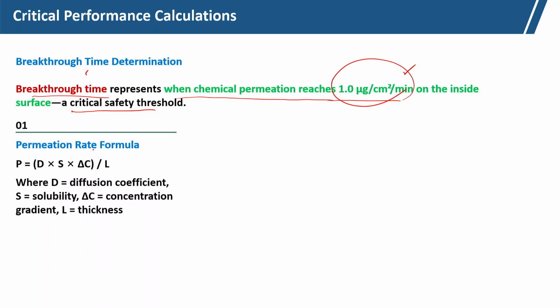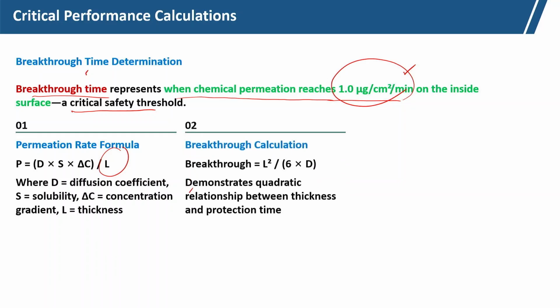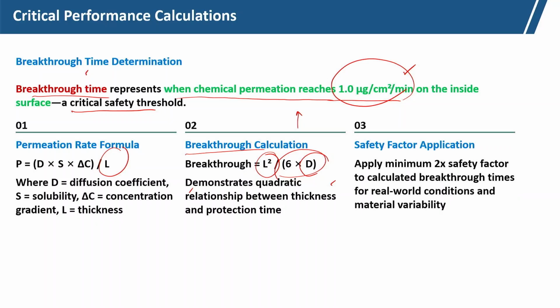The permeation rate formula is D S delta C by L, where D is the diffusion coefficient, S is the solubility, delta C is the concentration gradient, and L is the thickness of the material. And the breakthrough time calculation is L square by 6 D, that we have discussed. The breakthrough time is proportional to the square of the thickness. For the same diffusion rate, if we increase the thickness by 2 times, breakthrough time will increase by 4 times. And safety factor application: a minimum safety factor of 2 times is used to calculate the breakthrough time.